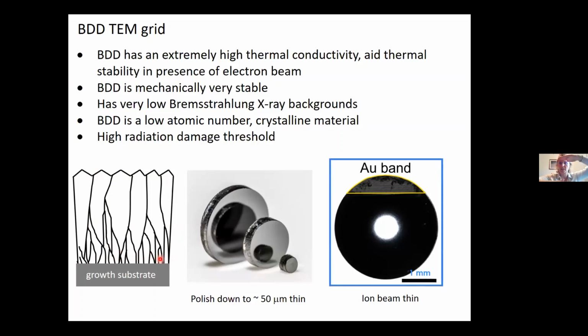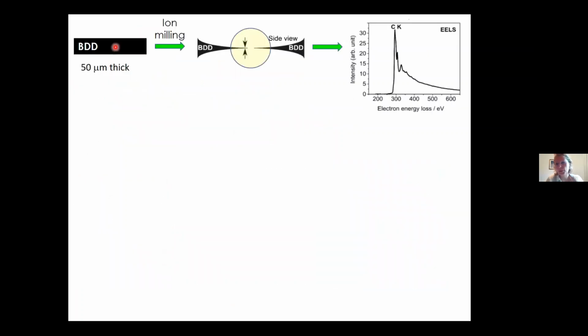So we take the thick diamond and we thin right down. From polishing, you can probably polish down to about 10 microns, but it's really challenging. You need very experienced, accomplished polishers to do this. We work down to about 50 microns because we want to handle this material as well. So we can handle 50 micron BDD.